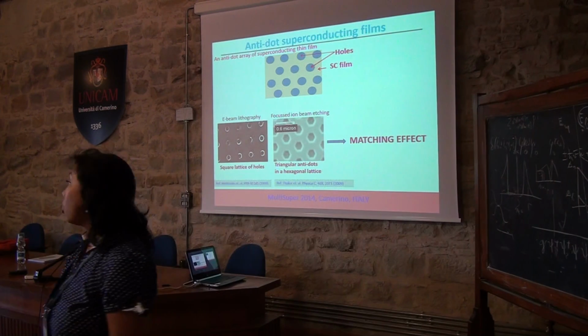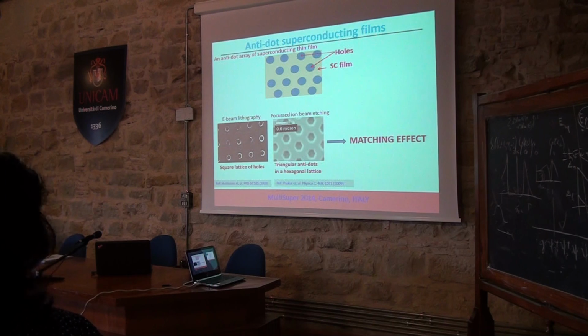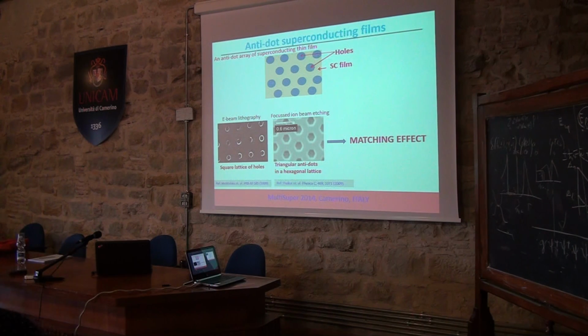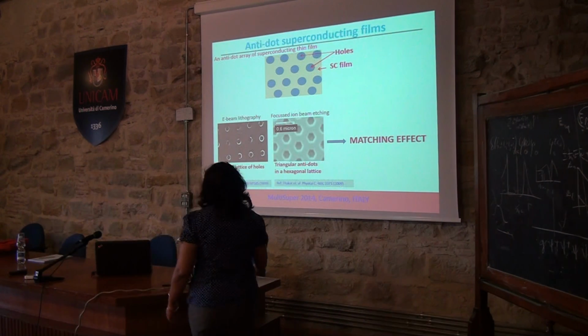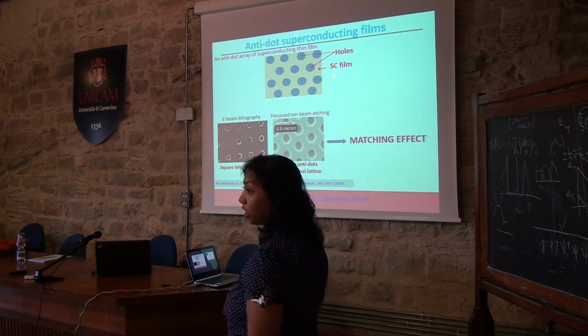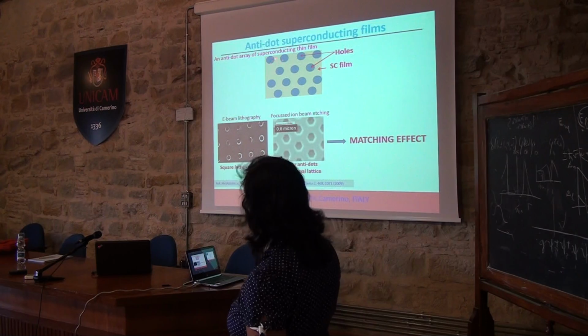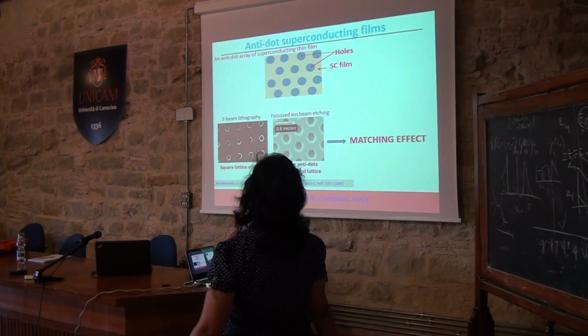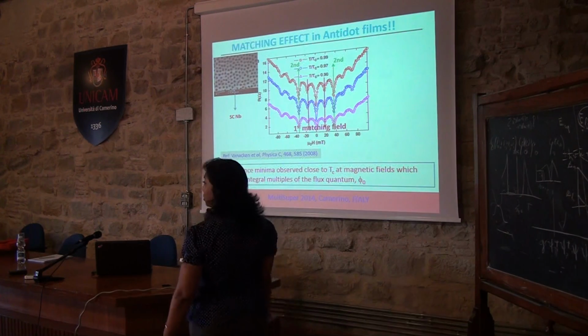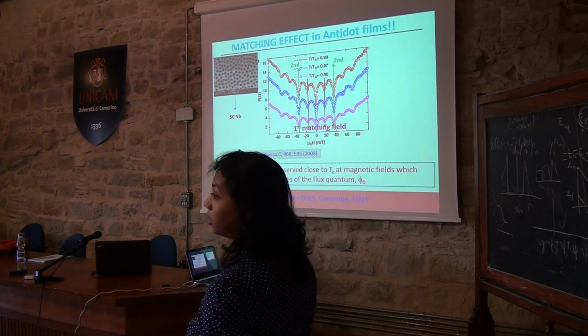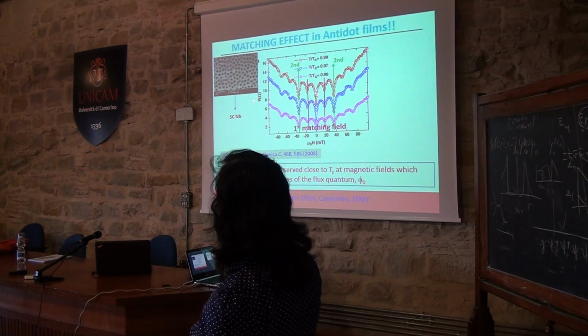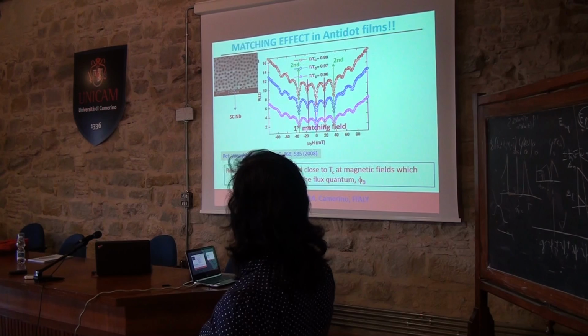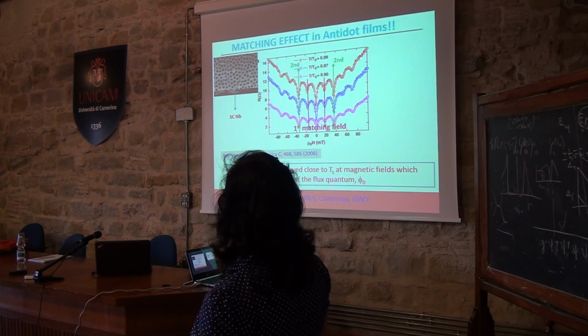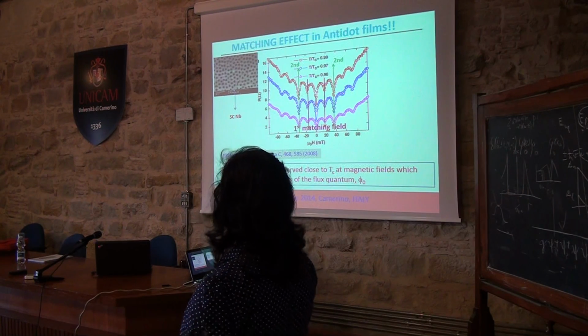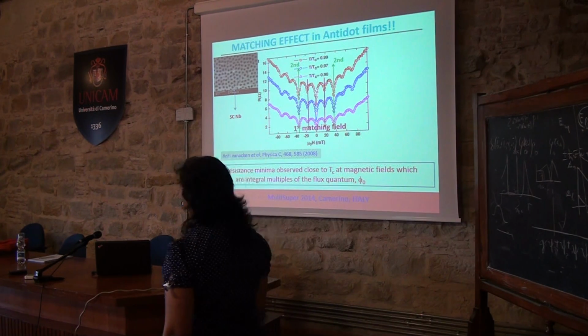Later, people also did experiments in superconducting films which had arrays of periodic holes. They again did it on different geometries which were synthesized by e-beam lithography. Here they were much larger structures. The superconducting width between the holes was not of the order of the coherence length. When they measured the resistance of these systems, they also observed similar effects. The effect was exactly the same. When you measure the resistance as a function of magnetic field, you start seeing oscillations in the resistance, and the oscillation period is exactly proportional to that of a flux quantum.